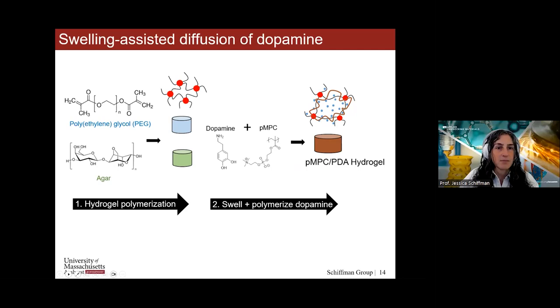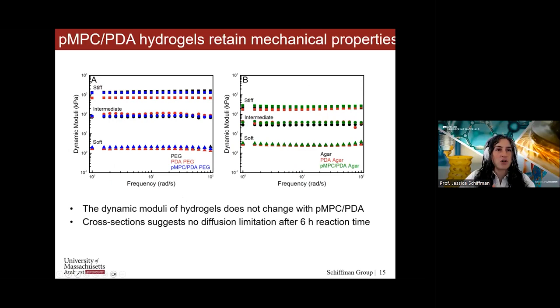Not to go into the details too much, but we did a lot of rheology to show that when we add our polymer zwitterion and polydopamine, it's such a small amount of dopamine, it doesn't even change the mechanical properties of these gels. So we'll find out why later, but we have three different gels that have different stiffnesses, and you can see all of our lines overlap. So this means our PEG gels by themselves have the same stiffness as when we have dopamine, as when we have our polymer zwitterions. And this is interesting because sometimes when we add polydopamine or this polymerized thin layer, it can make materials kind of brittle, and we didn't want that.